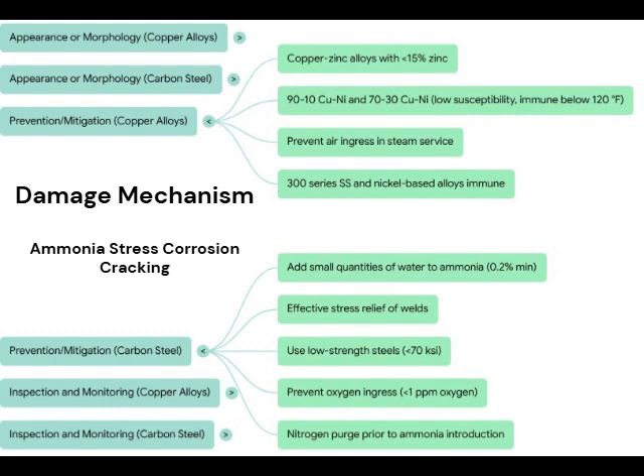And if you need total immunity, the sources say things like 300 series stainless steel or nickel-based alloys. They just don't have this problem with ammonia. Okay. But let's say you have to use brass, maybe in steam service where you might get trace ammonia, then the key is controlling that other trigger. Oxygen. Keep the air out. Limit the oxygen, you limit the SCC. It's amazing how simple that sounds, yet how critical. A tiny bit of air ingress ruining a whole bundle of tubes.